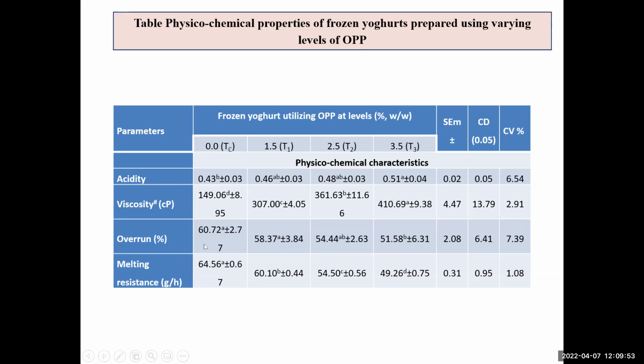Overrun is nothing but the additional volume of the frozen yogurt as compared to the initial weight of the frozen yogurt mix. In case of the control frozen yogurt, there is the higher overrun. As you increase the OPP, there is a decrease in the overrun. Generally, this is a drawback of frozen yogurt quality, but definitely it will increase the viscosity as well as the melting resistance.